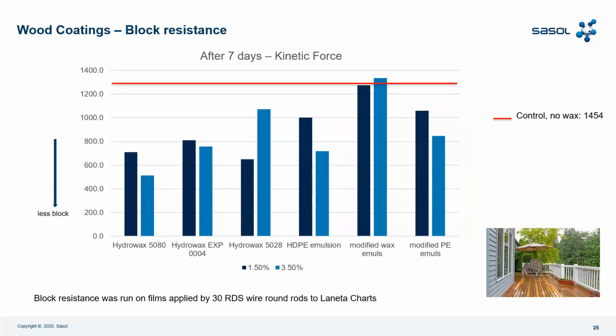Then we go on the kinetic force. Kinetic force, again, you need to read this graph with the lowest value being better. The best result was achieved by Hydrowax 5028 at 1.5%, then follow Hydrowax 5080 and Hydrowax Experimental 004. Again, you can see that also on the kinetic force, we have better performance with respect to the competition at 1.5%. At 3.5%, we have the best results with Hydrowax 5080 and then follow the other PE emulsions. Control without wax was 1454, you can see here. So the performance of our emulsion decreases a lot the blocking, so very good performance.